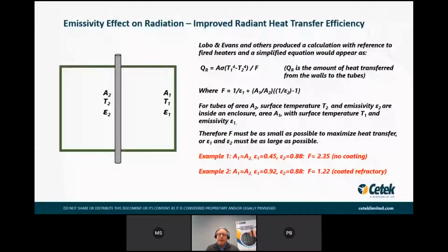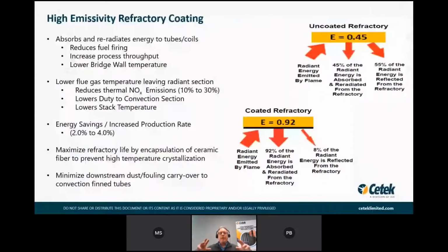So by increasing the emissivity from 0.45 to 0.92, F is then reduced, and therefore you're increasing QR. So it's behind the scenes, if you will, on the calculation side, but it is absolutely legit science for this technology. So long story short, high emissivity refractory coatings absorb and re-radiate the energy back into the process in a more useful wavelength. So we're reducing your fuel firing, therefore you're lowering CO2 in kind.